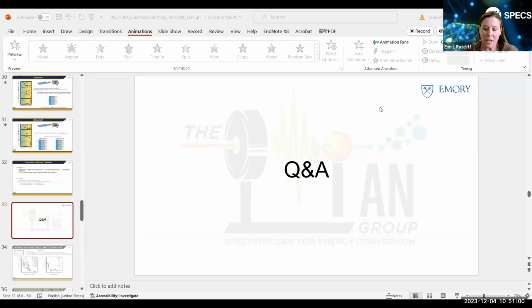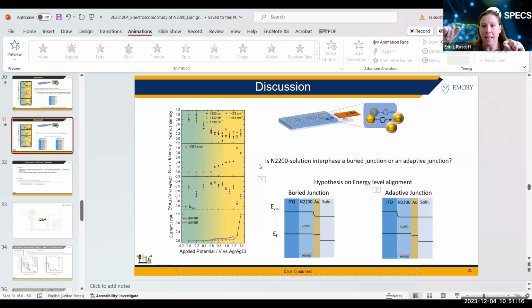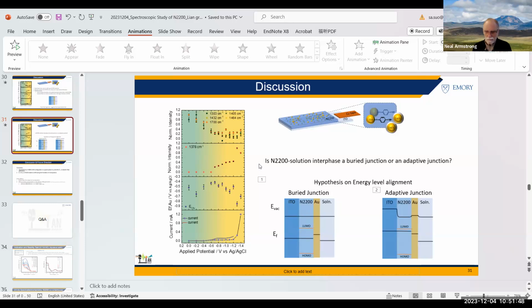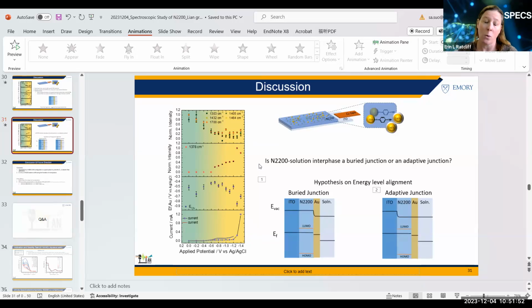One thing I saw at the very end, and I'm just going to react to it first, that's unique from solid state: generally what's assumed in the solid state is that the organic gets pinned to the ITO and to the metal, because it's such a low dielectric. And what you've suggested is that the gold is actually pinned possibly to the organic, which is quite a unique phenomenon. You'll see in the chat a hypothesis from Neil as well about whether it is acting as a localized cation or a localized polarization point or a local nano environment that's ultimately giving you that result. One question I have is, do you think this effect would scale with gold nanoparticle size?